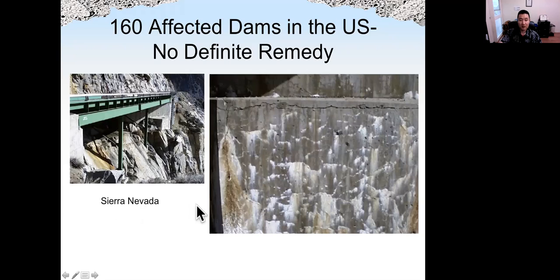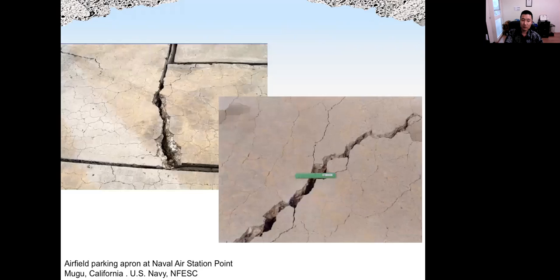All right. So here's another example of a dam damaged by ASR. You can see we have reddish materials coming out within the cracks inside the concrete. So that is the gel coming out of the concrete. So if you see something like that, you may double check if it's caused by ASR. Another picture of ASR: the crack is generated within the concrete, so very hard, if not impossible, to repair.